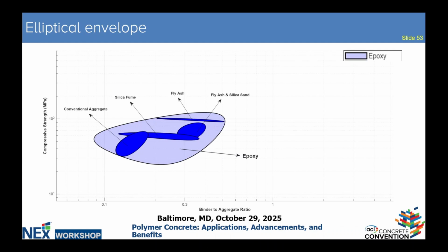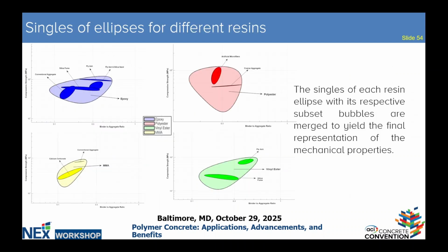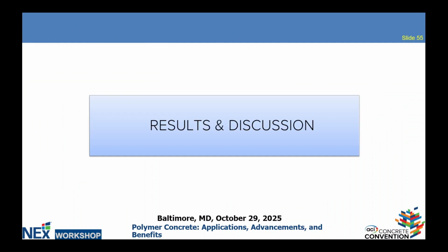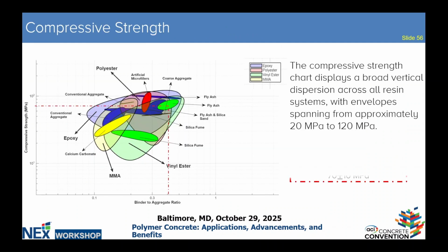So this is encased and assigned to our epoxy resin. So we have an epoxy resin with the subset data, aligned with your binder to aggregate ratio and with your compressive strength. So we did the same for the subsequent resins, which are polyester, vinyl ester, and methyl methacrylate, as we have here. So in our results and discussion, we are able to yield compressive strength data.